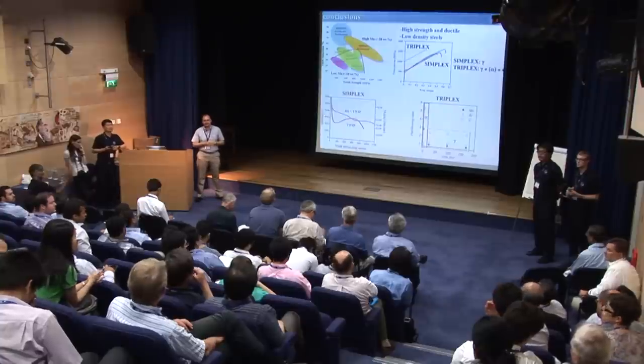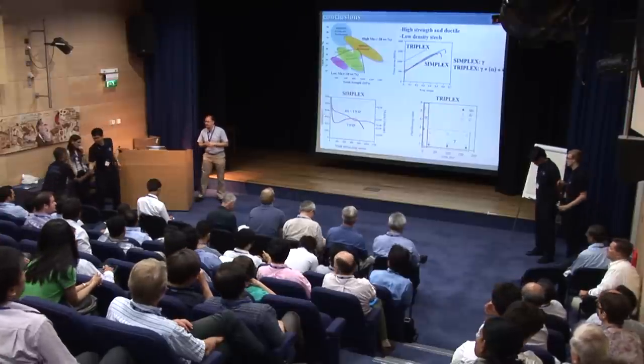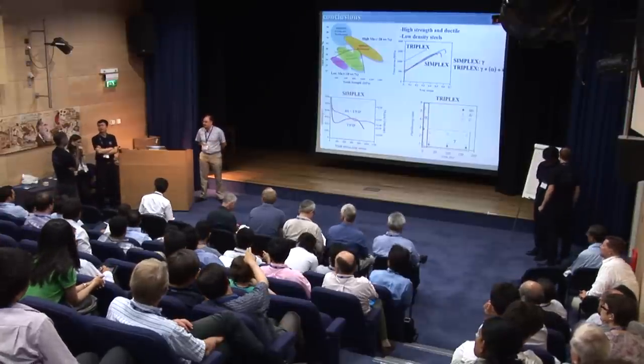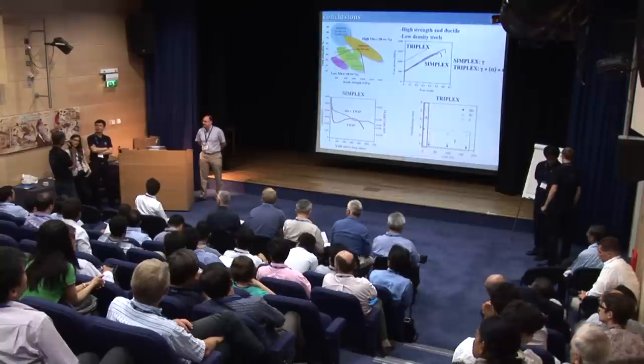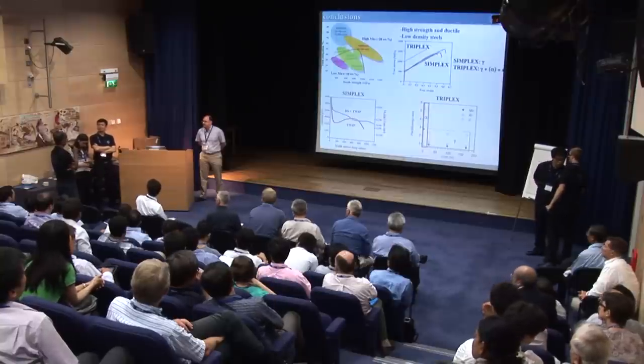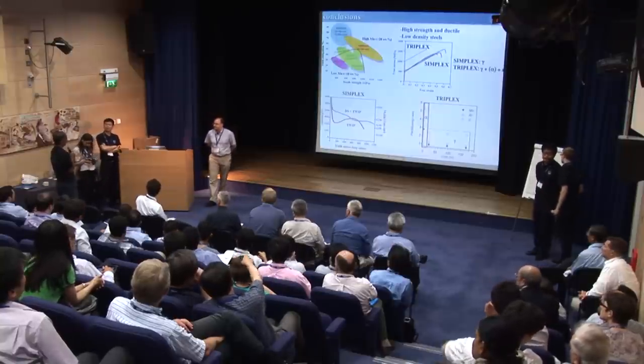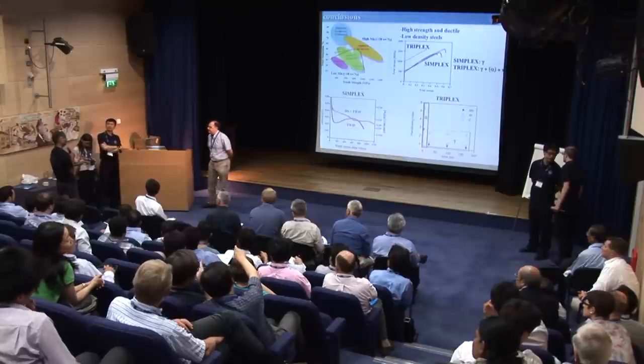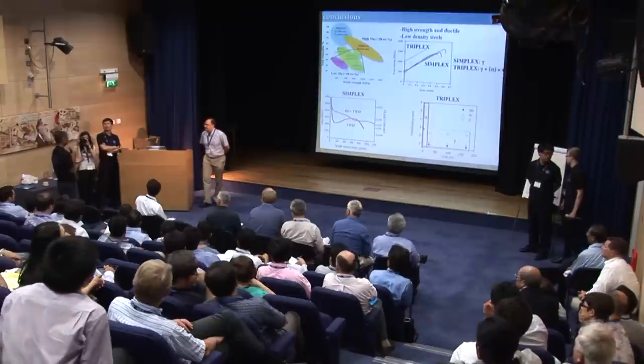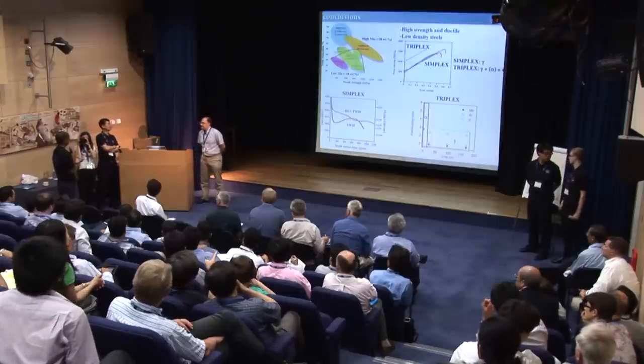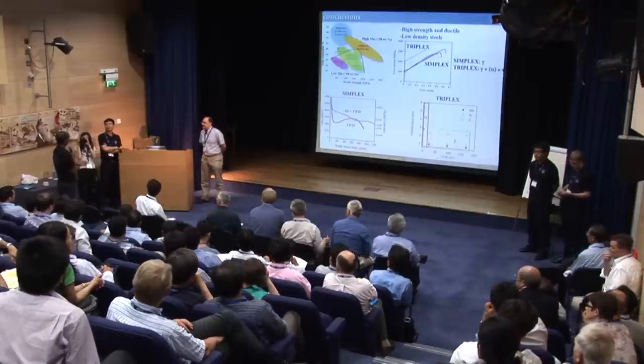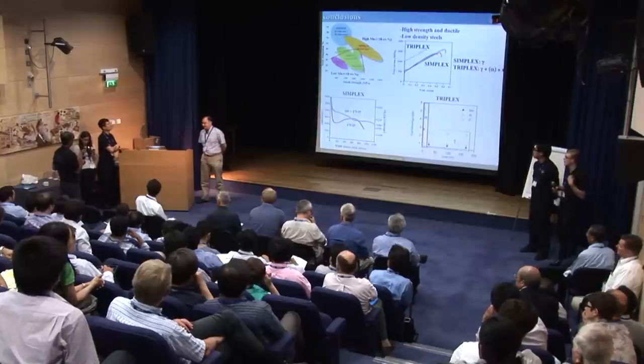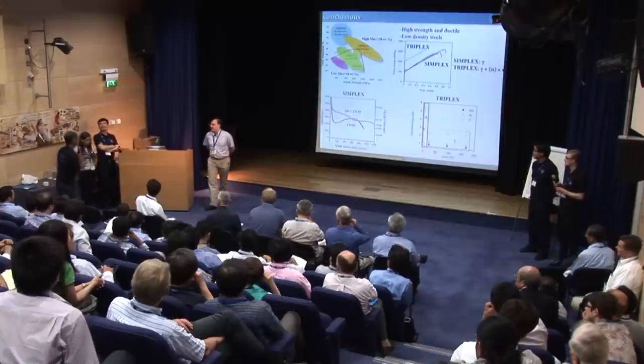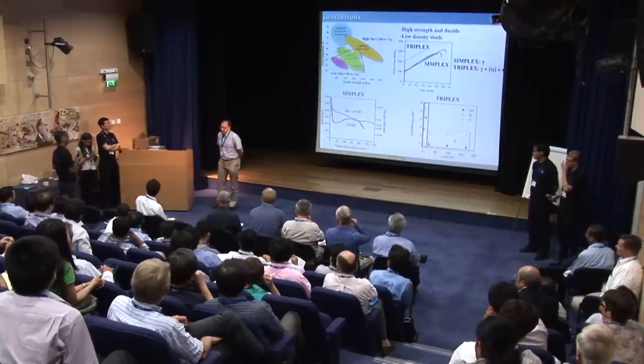Any more questions? So very interesting. You know, in the nickel-based superalloys, there's a very, very clever mechanism of controlling the lattice mismatch, which is that you vary the aluminum to titanium ratio. Is there a similar thing you can do with kappa? Hopefully. But what elements? Yeah, we still don't know.